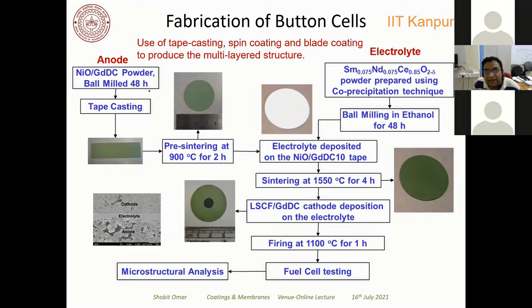So this is the button cell that we have fabricated, and you can see this is the anode, which is tape casted, and then the coating of the electrolyte is done through spray coating. A slurry is there, and you spray the electrolyte over it, and then you sinter that. You can see that the white color now changes to completely green, and the reason is that this is around a 15 micron thick film. Once you have a 15 micron film, it becomes more transparent once it gets sintered, which is why it transforms to green. Then you apply the cathode by brush coating. So this is the microstructure that you will get. You see, you have a dense layer of electrolyte and a porous cathode and anode.